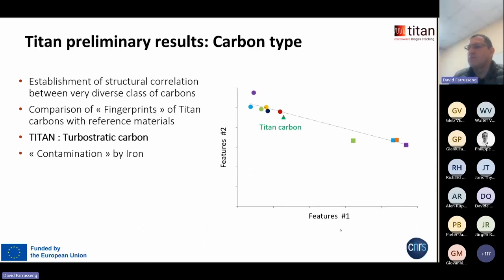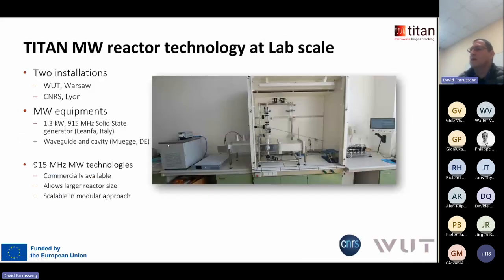There are many types of different carbons, and we characterized various carbons, including our carbon, and we figured out that the carbon we produce is of the class of what they call turbostratic, which is amorphous but still organized. It is not a graphite, but it's in between amorphous and very crystalline graphite. And for that, there are some applications. There is a but. The but is that, of course, the carbon we produce is contaminated by some iron, and that has consequences on the market and the value of the carbon.